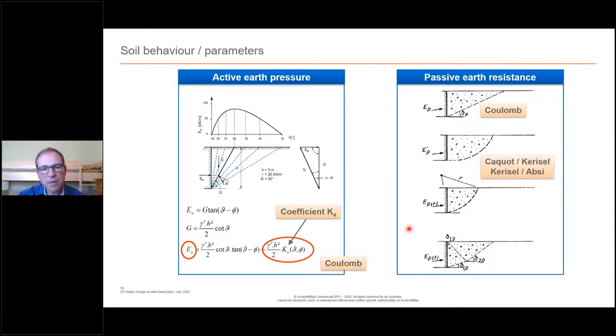So how to determine the Ka and the Kp, which is the active and the passive? There are different ways. Very often the Coulomb method, so the formula from Coulomb, is used for Ka and for Kp. But if you have a very high friction angle, like a phi of 35 degrees, it might give you a Kp which is too high. So for the passive earth resistance, normally what we recommend is to use the tables from Caquot-Kérisel or Kérisel, it's almost the same, which give you a good approximation, which is not as optimistic as the Coulomb for the very high friction angles. But if you have a phi of 30, for instance, you'll get almost the same value. And the difference is only the failure surface. So Coulomb assumes that you have a straight line, whereas the Caquot-Kérisel assume that you have a straight line combined with a logarithmic spiral, which gives a different solution.